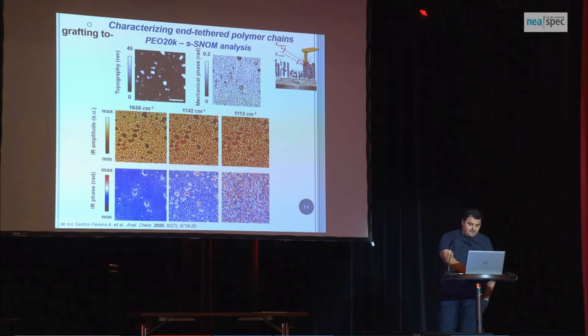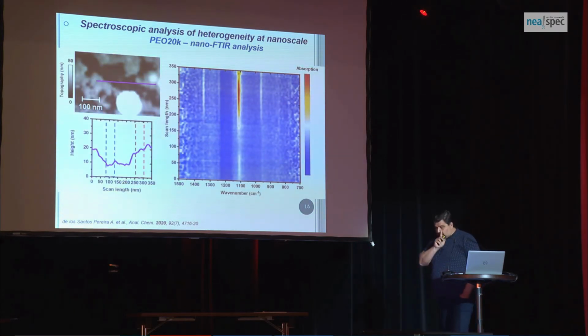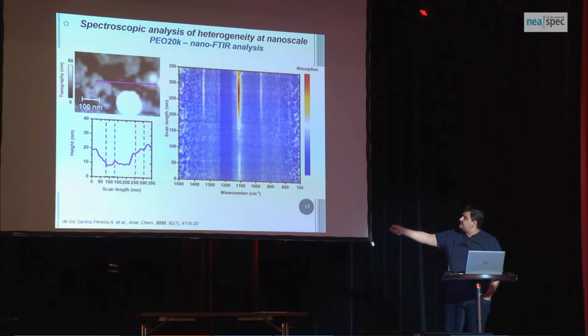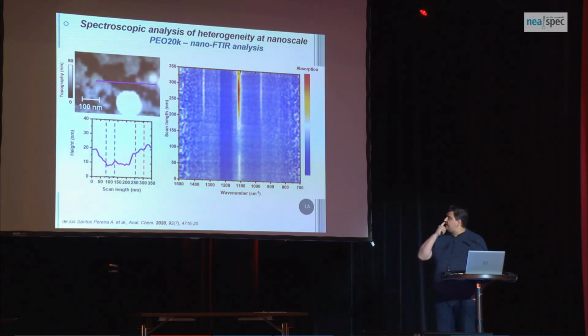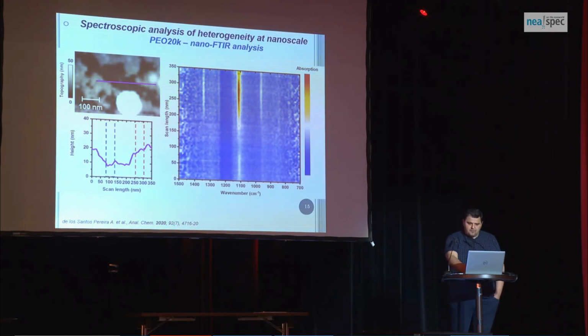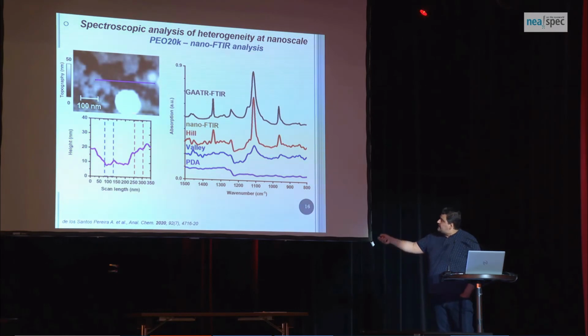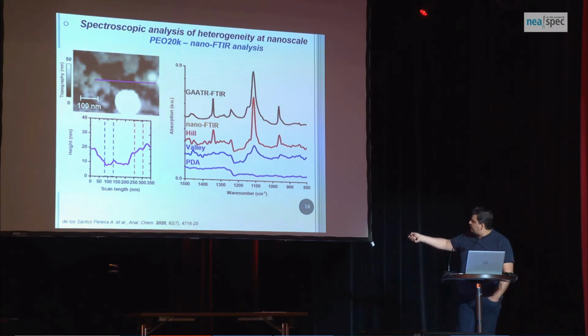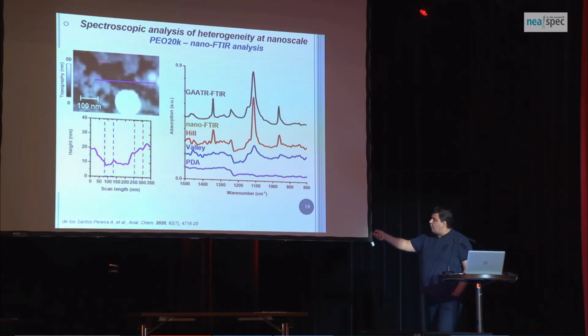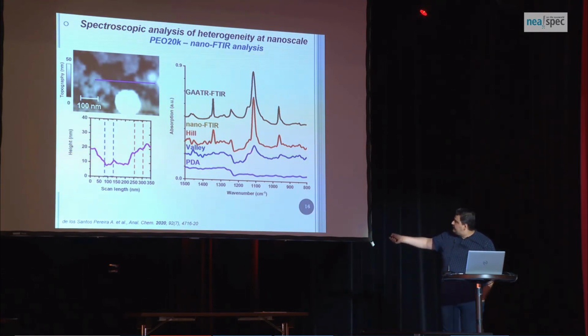Good. Then somehow we've agreed that we need to perform some nano-FTIR analysis and go over this line, from something which we call the hill, an area which we call the valley, and an additional hill. And with a strong push of Fritz, we were capable not only of saying that in the valley region we really have polyethylene oxide, which would not be visible or obvious when we look only at the height image of the AFM, but we were capable of observing that the valley also has the spectral signature of the PEO.